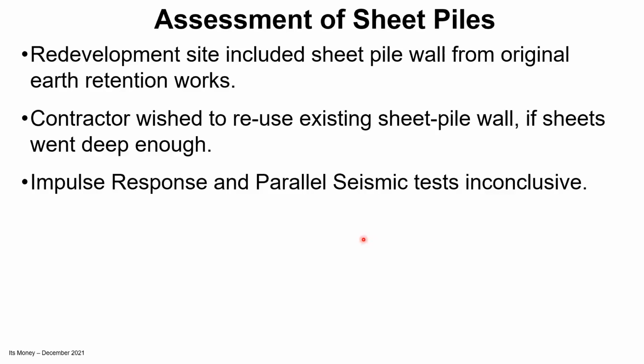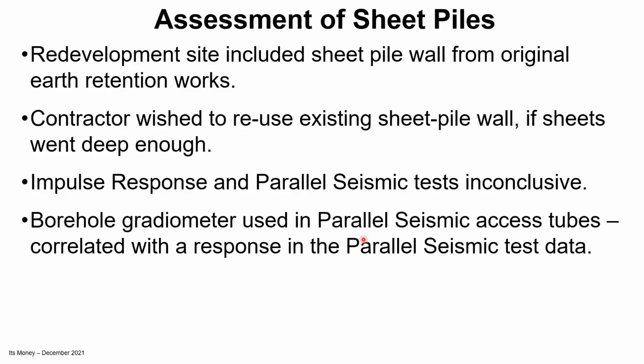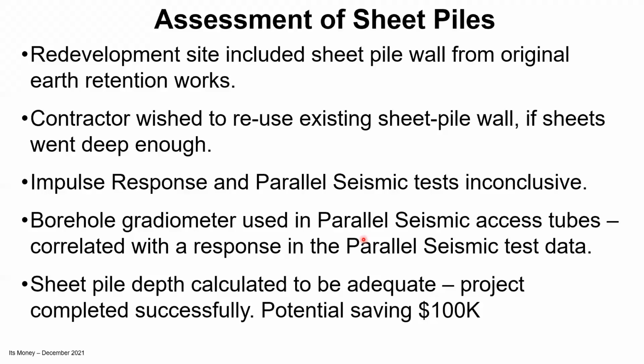Impulse response, because the signal basically just got dissipated by the sheeting. The surface area relative to the cross-section area is so great that all the energy gets lost within a few feet. The parallel seismic tests showed a number of variations because there was fill material involved. We thought we saw a response from the base of the sheet, but we couldn't detect it reliably enough to be positive. So a borehole gradiometer was used also, and that too produced a number of responses, but the strongest response did correlate with the response in the parallel seismic data. So based on that, the sheets were used.